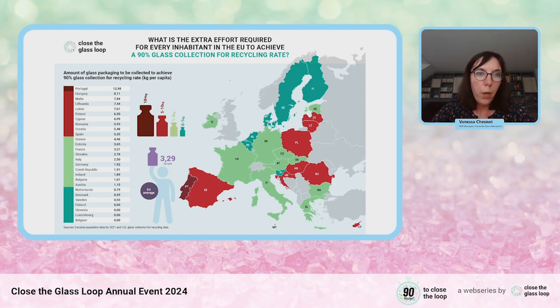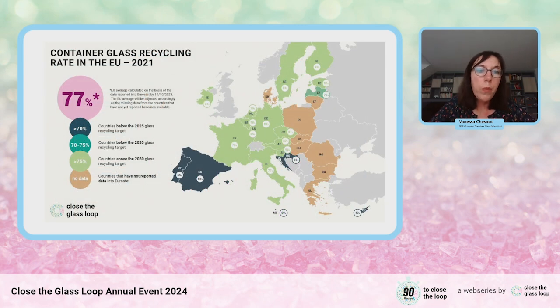So that's another perspective. And also important to keep in mind that with Close the Glass Loop, we have a voluntary commitment to achieve a 90% collection. But we also have a mandatory 75% recycling rate to be achieved by 2030 in the packaging waste directive. So that's an obligation. And this map reflects the recycling rate that is reported by EU member states to Eurostat. And so on the basis of the countries that have provided data for 2021, a few have not, the average EU recycling rate was 77%. So that's already above the PPWD target. And just to note that we are updating this map whenever new data are available.